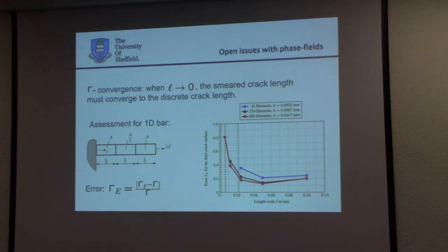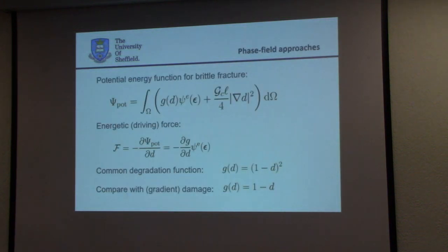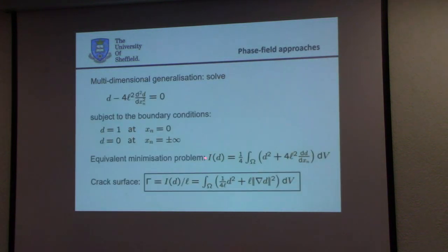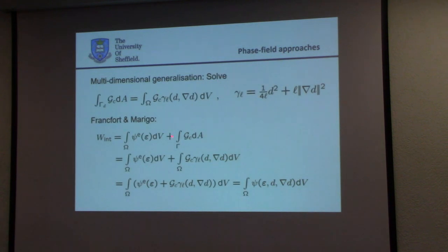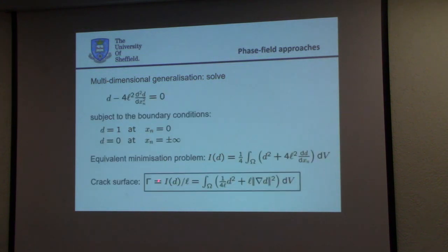Well, we have said at some point, I go a little bit back, we have said here that we approximate this line integral or surface integral by a volume integral. And that this crack surface is defined as this functional divided by L, and that upon mesh refinement, this expression for a smeared crack should approximate the discrete one.